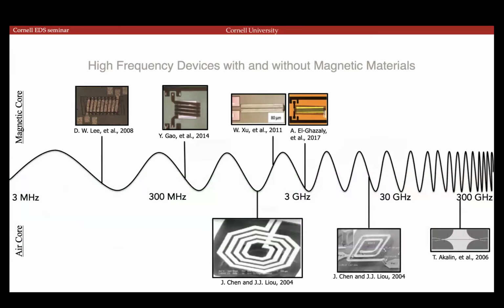So far, if you compare what has been done in the wireless spectrum magnetically, all of the magnetic devices are operating below about 3 gigahertz, below what is called the ferromagnetic resonance of a material. If it's below that resonance frequency, then you get a large permeability. But as soon as you try to operate the magnetic material above the resonance frequency, all of a sudden it becomes a lot more lossy. So what people do instead is just simply forego the magnetic material and make an air core device or inductor of sorts.